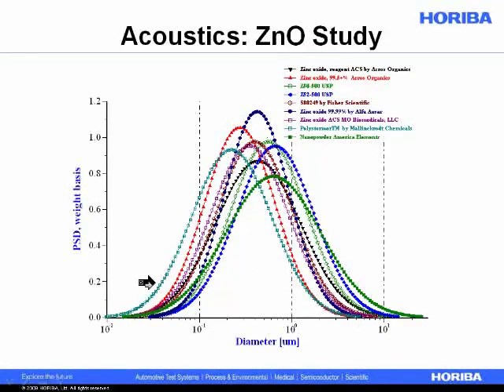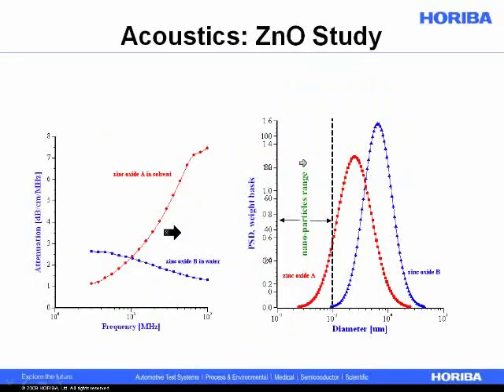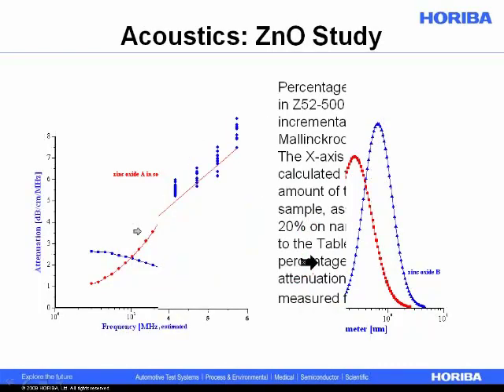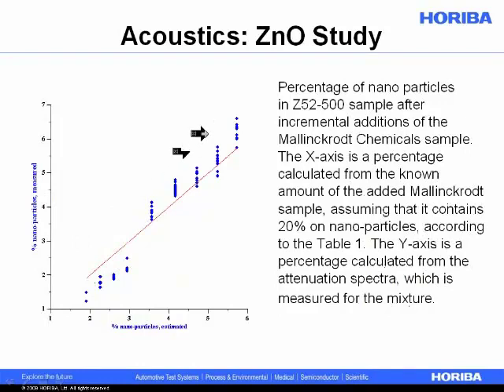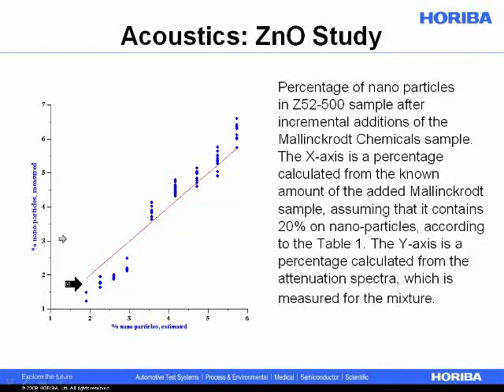This is the data of all the individual materials. A direct addition test was performed to look at the percent of very small particles. We see a significant difference in the attenuation spectrum on the left for the largest and smallest samples used in the study, and a significant difference in the particle size distribution on the right. This would be our base, and this would be our dopant. As we added small amounts of the dopant, we compared the calculated percent of particles below 100 nanometers to the measured value, and we see a very tight fit across this curve down to 2%. So acoustic attenuation proved very successful at detecting the presence of these nanoparticles down to a couple of percent.